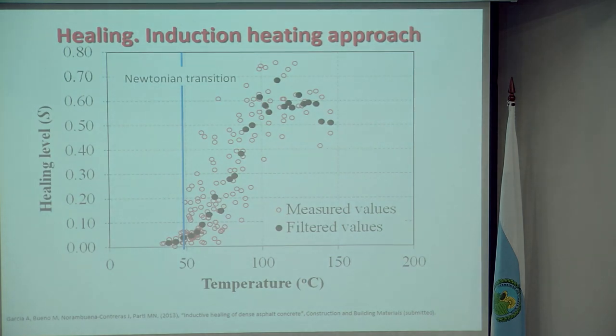What do the results look like? Well, the results look extremely promising. There is a threshold. Induction heating does require you to actually exceed some form of minimum temperature. That will vary depending on how much of the steel wool or steel fibers you put into the material. But for this particular set, we're looking at about 0.1% by mass. We would have to get above roughly 50°C before we saw any effect.